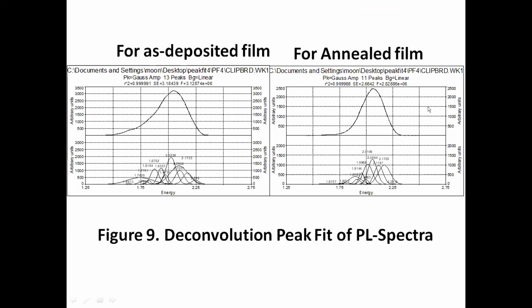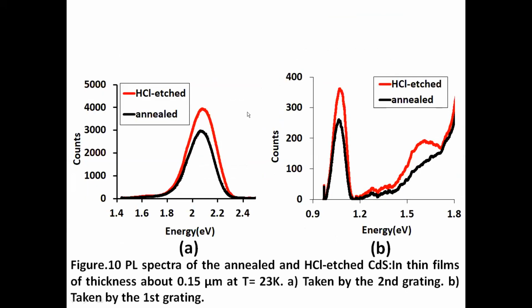Here are the PL spectra of the HCl etched film and the annealed film. You see the shoulder is removed approximately, and you see the effect of annealing is stronger in removing the shoulders in the red tail. The effect of annealing is stronger than the effect of etching.